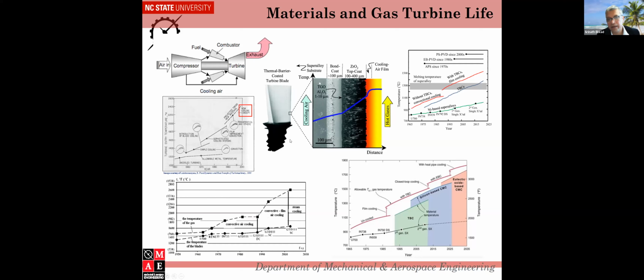And as you can see, now the surface of the blade is a lot more complicated too. If you look at this, this is the metal, which is titanium or a nickel-based alloy. And then you have a bond coat, and then you add the yttrium-stabilized zirconium layer, which is basically what is called a thermal barrier coating. And then, of course, you have the cooling air.